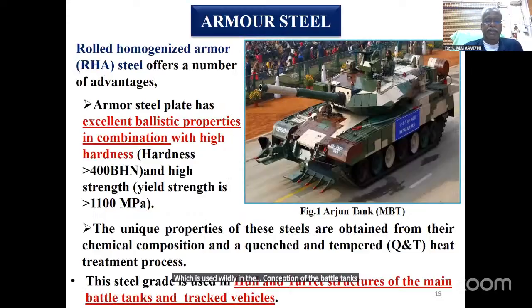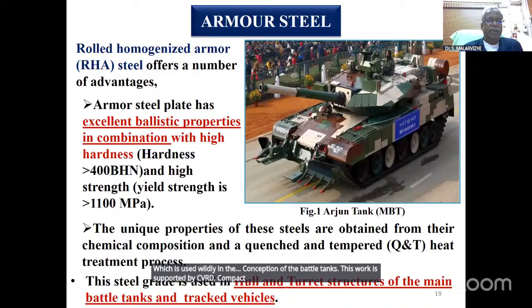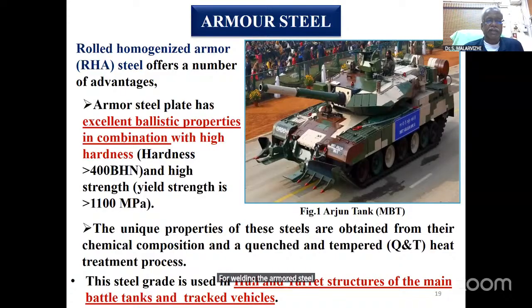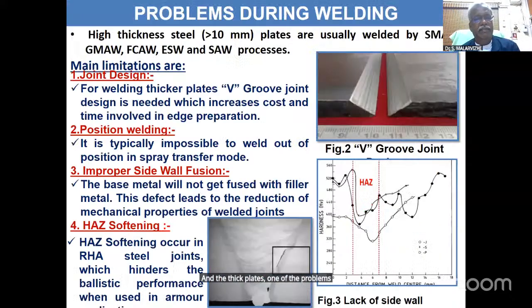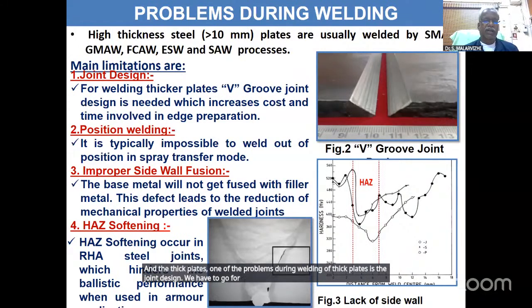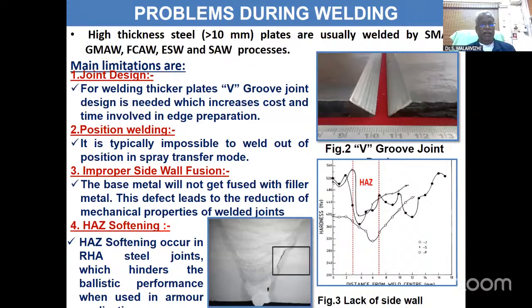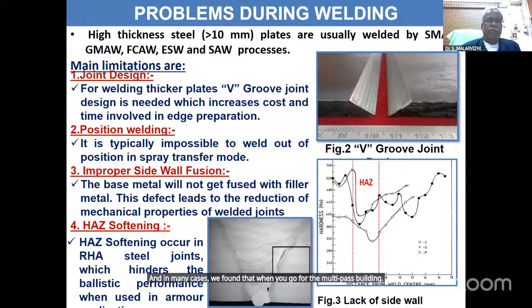This work is supported by CVRDE, Combat Vehicles Research and Development Establishment. For welding the armor steel, we use this process. One of the problems during welding of thick plates is the joint design. We have to go for a single V groove or double V groove. And then position welding: it is impossible to weld out of position in spray transfer mode. And in many cases, we found that when you go for multi-pass welding, improper sidewall fusion is one of the problems.